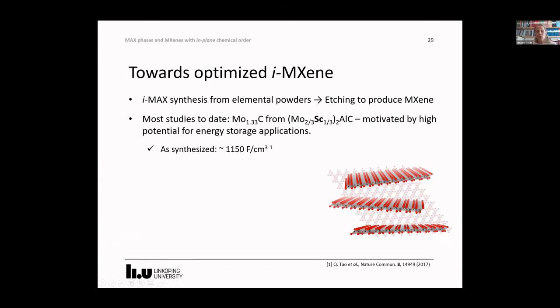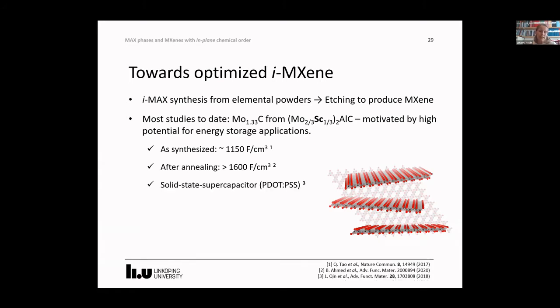As I mentioned before, the as-synthesized MXene, when it was tested for the first time, gave a capacitance of about 1150 farad per centimeter cubed. This could be increased after annealing to more than 1600. We've also used the Mo MXene in solid-state supercapacitors, mixed with PEDOT:PSS, and more recently we have formed composite electrodes with cellulose, where we've had a high MXene mass loading, and that has shown really good results.